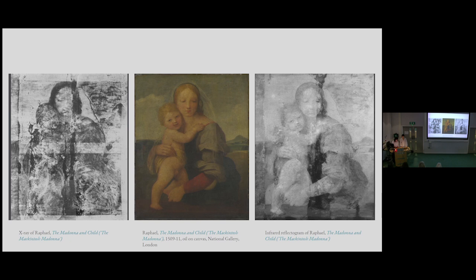During the 19th century, canvas became the preferred support for panel paintings, although early criticism of this method had already emerged. By 1834, the transfer of panel paintings to canvas was recognized as a challenging and hazardous procedure. Many historical canvas transfers necessitate additional conservation treatment, particularly those executed improperly. A small error in an intricate procedure can irreversibly damage the paint layer. Due to its invasive nature and removal of original material, this technique is considered today as a very last resort, if any.